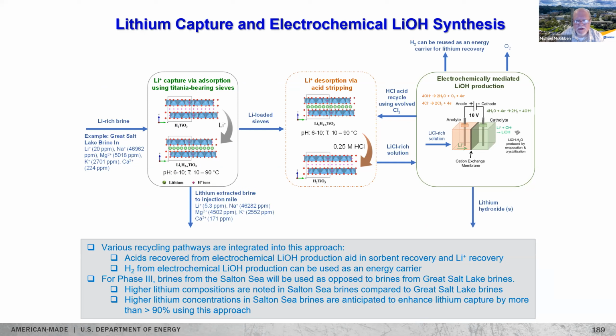In the next phase, we will test it on Salton Sea geothermal brines with an order of magnitude higher lithium concentration at more realistic power plant temperatures of 95 to 105 degrees centigrade. It is important to note that the endothermic nature of the absorption ion exchange reaction should promote greater selectivity and capture efficiency at higher temperature and lithium concentrations. So we expect higher recovery under more realistic Salton Sea geothermal brine conditions.